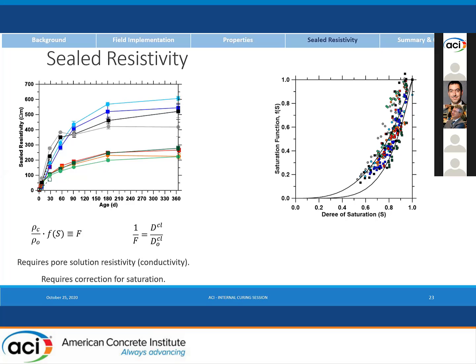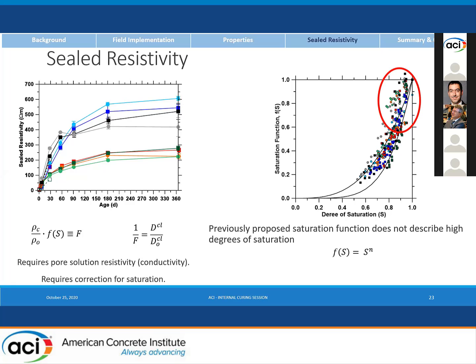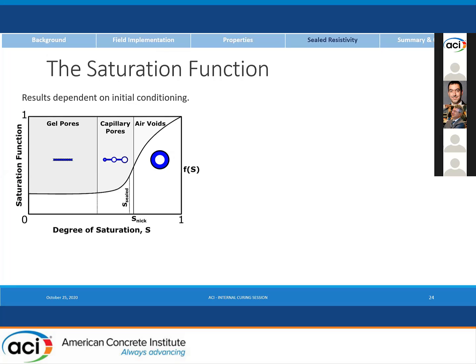And then we tried to fit what we thought was the S to the N type of saturation function, and we see that it doesn't really fit. So that made us kind of start to rethink, well, what does it actually mean for air-entrained concrete? And so we've come up with a different model. I've just shown it here conceptually, but actually I've also in my work gone through a series of electrodynamics calculations that do indeed support that this is what the shape should be.